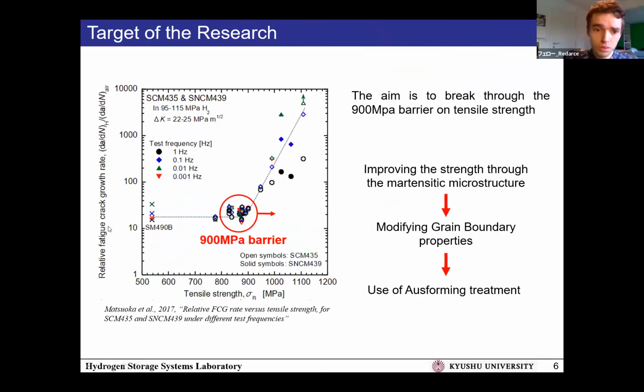The target of the research was to move this zone in the graph more to the right, with higher tensile strength. This graph shows the relative fatigue crack growth of metals in hydrogen environments. We can see that the fatigue crack growth is quite okay until a tensile strength of materials over 900 megapascal, and from there the fatigue crack growth rate increases a lot. So the goal is to have this knee appear at, we are aiming for, 1 gigapascal, and if possible we want to try to go up to 1.1. And the way to do this, we decided to focus on the type of ausforming treatment.